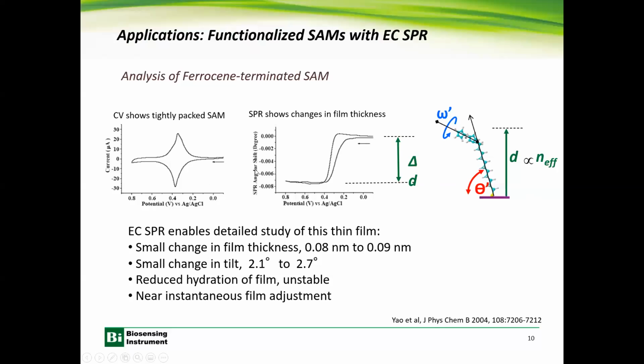And then by oxidizing or reducing the ferrocene, you change the conformation structure of the thiol layer, which is caused by a slight tilting of the molecules standing on the surface. So a very small change. The angle tilts from 2.1 degrees to 2.7 degrees, and such a small change will give a change in the film thickness of 0.08 to 0.09 nanometers. And this is a very, very small change in the film thickness. However, because of the very high sensitivity of the SPR detection, you can actually determine and measure this change caused by the oxidation state of the ferrocene group by the charge transfer.